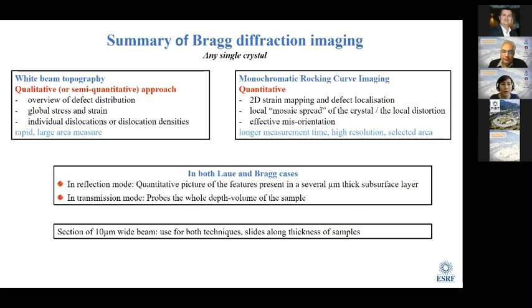The white beam topography gives the qualitative approach for the defect distribution or the global strain or stress. And we can see as well the individual dislocation or dislocation density. The rocking curve imaging gives more quantitative information like the 2D strain mapping, the mosaicity, the local distortion or the effective misorientation.